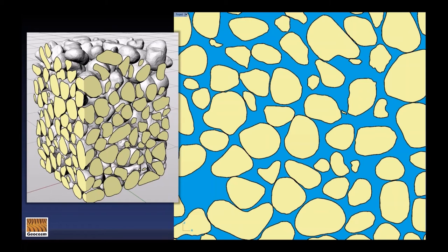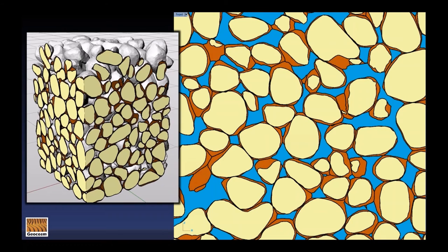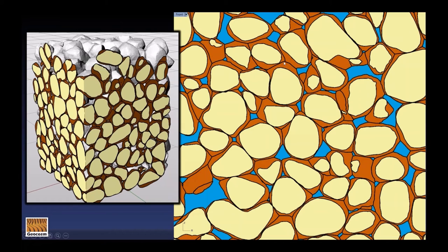So what we're looking at here on the left is a slice taken through our 3D grain pack, and on the right is a 2D slice from that 3D grain pack, where obviously the blue here represents pore space and the yellow represents quartz grains. And now what we're going to do is to progressively cement up this pack with quartz cement, shown here in orange. And so you can see what we are very satisfied with is that the geometry of the contacts between these overgrowths is very reminiscent of what we see in nature. We often see these sort of triple junctions in quartz overgrowths and pores. And also the geometry of the pores themselves is quite reminiscent of what we see in very highly quartz cemented quartz arenites.